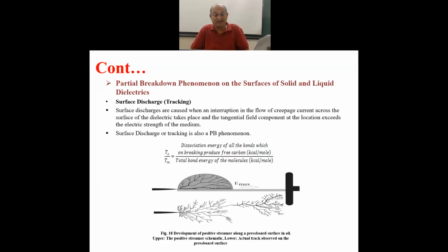there is not just a streamer but even leader channels formed towards the opposite electrode because of the high intensity of current in the breakdown channel or discharge channel. The intensity of current would determine whether it is streamer or leader breakdown. We had seen the leader breakdown, which could be produced at a very low few kV only in the laboratory on the surface of simple glass.